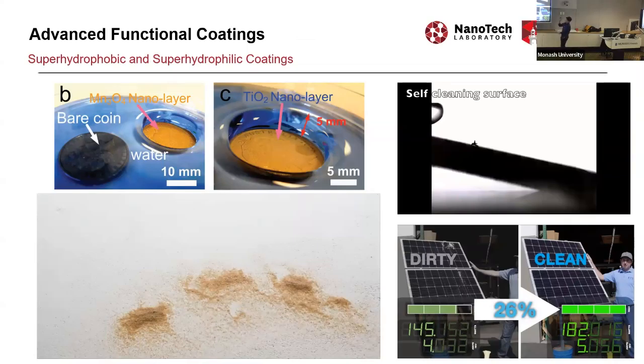Moving forward, we do a lot of hydrophobic surfaces. Again, this is the same nanofabrication technique. You can see a coated Australian dollar coin in colored water. The bare coin is just covered by water, but the coated one, regardless of whether it's manganese oxide or titanium dioxide, can repel the water, up to 5 millimeters.